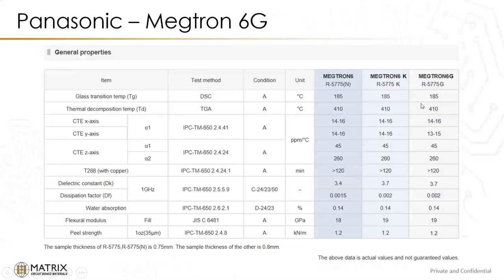You can see the properties are exactly the same down the line between the two products. And of course, the UL between all three are the same because it is the same resin, and that's all UL cares about. So the K and the G are equivalent in performance and property, and you'll see the only difference here is basically a change in the Dk because of the low Dk glass. You get a bump in the Dk and a little bit of bump with the DF as well, but the primary purpose of the low Dk glass is faster signal performance with the lower Dk.